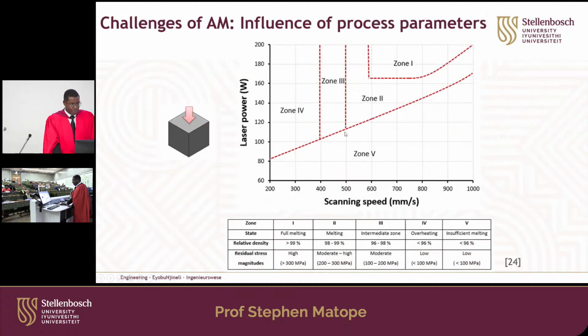And we also came up with a map now. Say, if you would like to have almost 100% density, because normally if you build layer by layer, laser fusing, sometimes there will be pores in between, porosity is an issue there. But we found that if one would like to achieve that, you can work with zone 1, where your scanning speed must be at least 600 or higher, and your laser power should be at least 150, 170, or higher. Then you can have almost 100%, 99 to 100%.